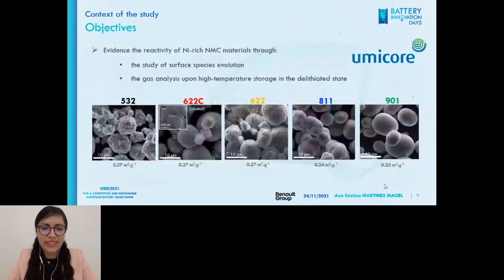So for my thesis, the objective was to evidence the reactivity of nickel-rich NMC materials through the study of surface species evolution to clarify the mechanisms, and through gas analysis upon high temperature storage in the delithiated state. For this, we used 5 different materials ranging from 0.5 to 0.9 nickel content, which came from Umicore. One of them was a coated material, the 622C.